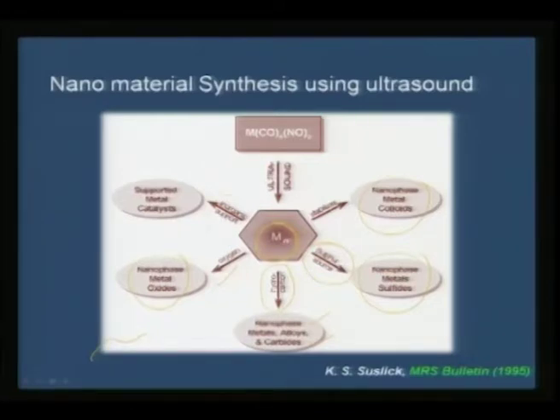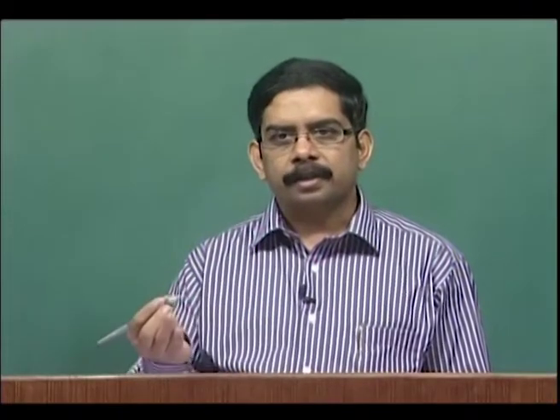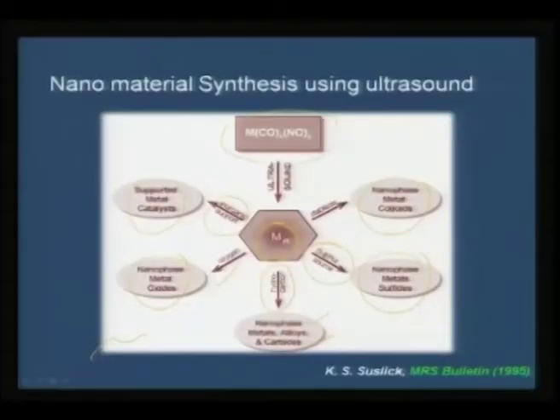And if you are going to take an inorganic support, then you can get a supported metal catalyst. For example, if you want to trap some iron nanoparticles in alumina support or silica support, then you use such an inorganic support to get this metal catalyst. So just starting with one particular starting material, using ultrasound you can play around with a variety of inorganic compounds, and for a good review you can look at this, which appeared as early as 1995.